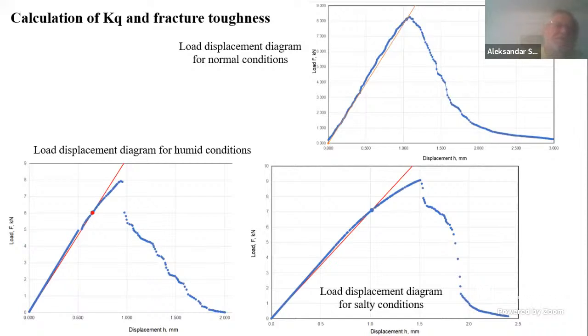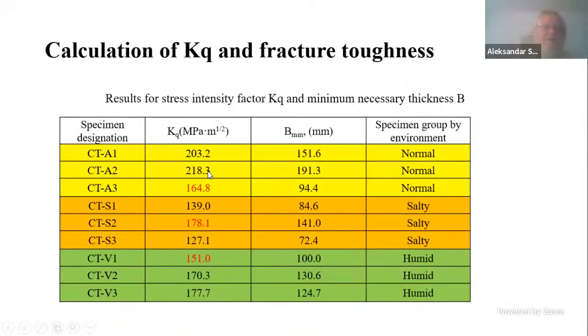Now, for the fracture toughness, these are 3 diagrams that we typically obtained, once again, for 3x3 experiments. This one is for normal condition, humid and salty conditions. And here are the results. So KQ, once again, in all 3 conditions, we had one specimen which was a bit different from the other 2. But we counted on average scale this effect of salty or humid conditions, and found out once again that normal is the best, then comes humid, and then comes salty.